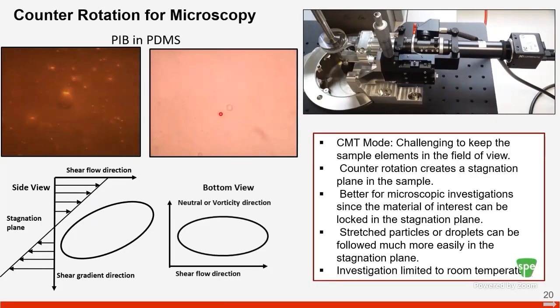So you cannot really look at these structures for a long time. But using this counter rotation mode, one can create a stagnation plane. By creating that zero velocity field, I can visualize these structures for much longer. The rheo-microscope setup is shown here, where you can probe the structures both from the side in this video on the left and also from below, so you can probe both in the gradient direction and the vorticity direction. This is PIB and PDMS, by the way.